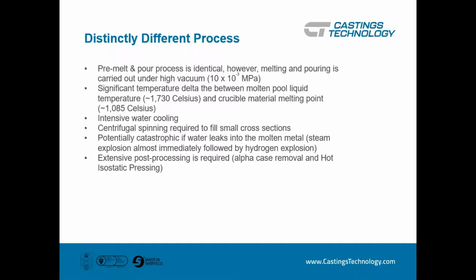One of the reasons we go into a cold shell is to keep the alpha case thickness to a minimum. In America, they tend to go into hot shell, which propagates more alpha case, more to remove, but from their perspective, that's just quicker and easier. For us, we like to minimize the alpha case and the grain growth within the material as well. So that's why we go into a cold shell.